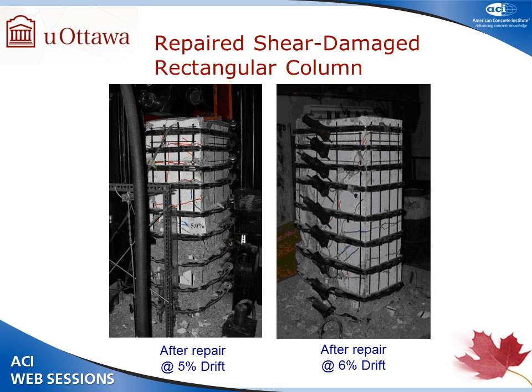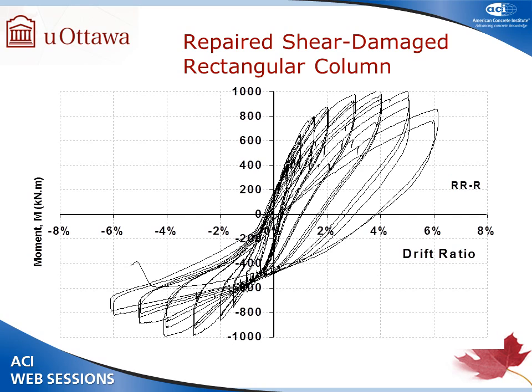And then we were able to go up to 5%, 6% with some visible damage, but it did improve quite drastically. However, we got a funny-looking hysteretic relationship because column was damaged in one direction. It never was able to recover. In spite of that, we were able to develop strength. Initial strength was 800 kN.m. It went up to 1,000 kN.m because it did clamp cracked concrete, and it contributed to aggregate interlock as well as providing additional shear steel because, after all, this was a high-strength prestressing strand.